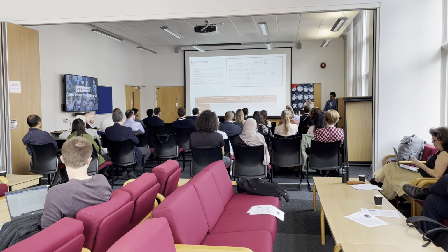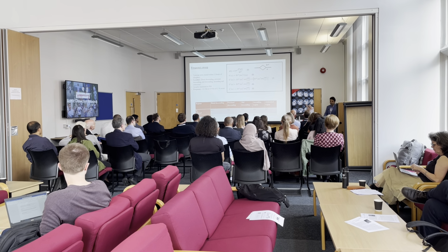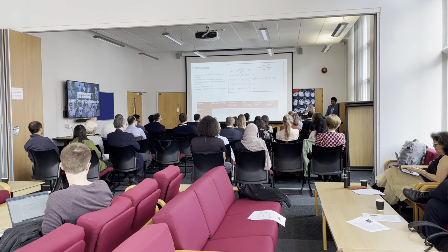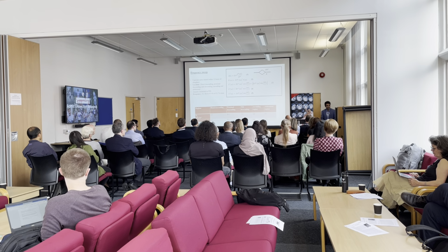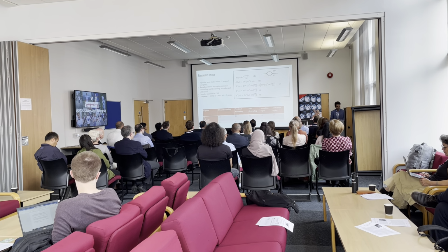the inertia. And in the case of inertia, what happens is that there is a slippage between the top plate of the rheometer and the aortic samples. So on the right hand side, you can see this particular equation number 1. Equation number 1 is the stress strain equation of a